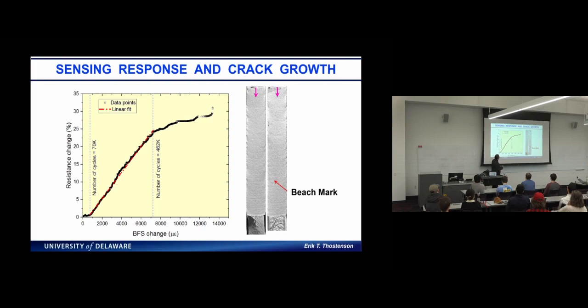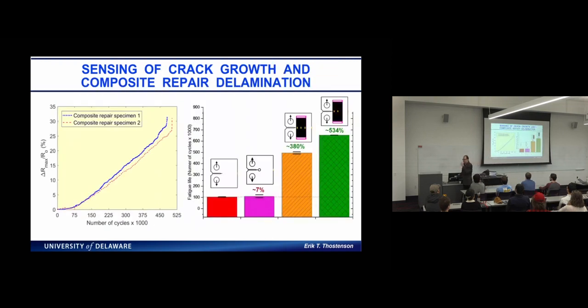And actually, you see it starts to become nonlinear at some point. That's actually because we fatigued the strain gauge. But the sensor continued to work. Of course, you can't put a back face strain on a bridge, right? But so we were able to take this, and we showed this very uniform, very repeatable ability to sense. This is a number of cycles to failure and our change in our electrical properties, and we know that that's quite linear with the crack length.